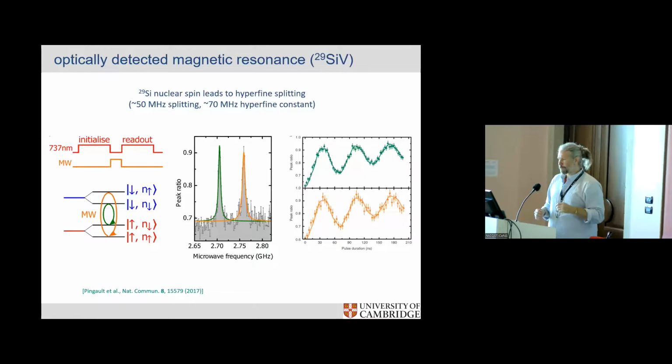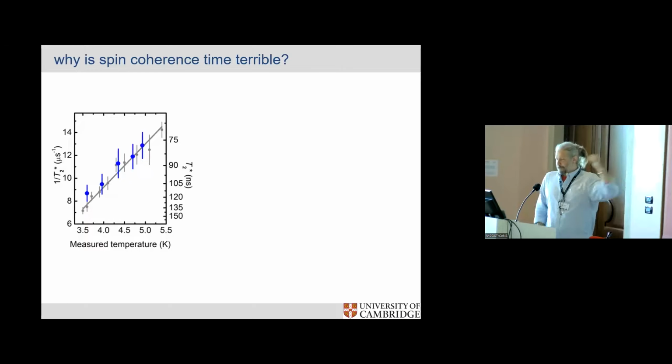So here's an example of driving the electron and nuclear resonances by using ODMR, and you're able to see Rabi oscillations and all that. So it gives us access by using optics and microwave combination, just like the NV center to a certain extent. And then this measurement happened. So what you're seeing now is temperature versus the quality of that electron spin, a T2 star, not decoupled, not corrected, but as is, the T2 star of the electron spin.